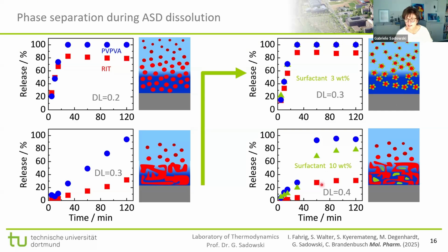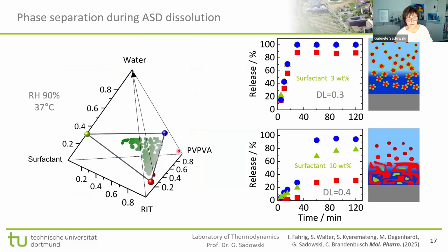And the explanation again is a phase diagram. Let's look at thermodynamics. We now have four components. We have the PVP-VA, ritonavir, and water. This is what we had before, but now we have also the surfactant. And so we did a PC-SAFT calculation, and indeed, the PC-SAFT calculation suggests that we have a demixing in three phases, as we assumed looking at the release profiles, and also the experiments say this.